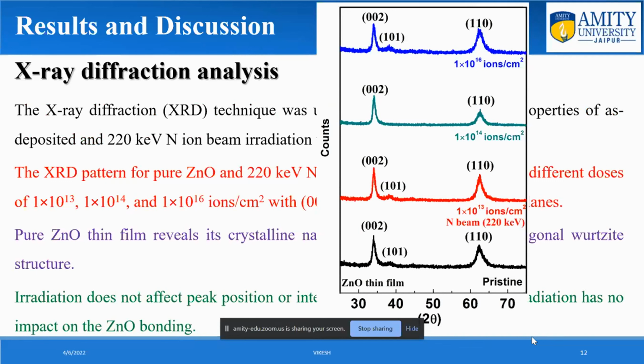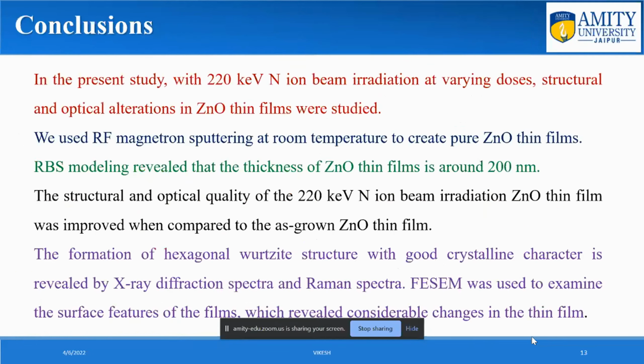Pure ZnO thin film revealed the crystalline nature and demonstrated the hexagonal wurtzite structure. Irradiation does not affect the peak position or intensity. This demonstrated that irradiation has no impact on ZnO bonding.